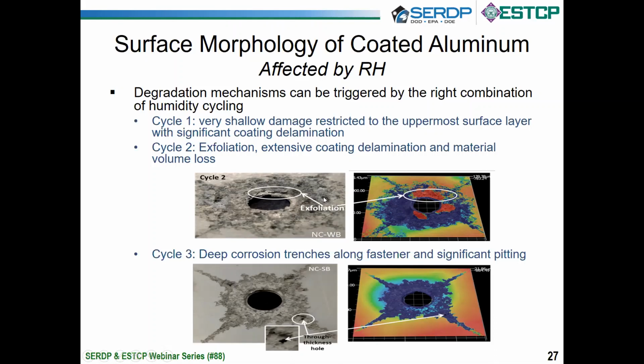And the thing that you notice in this test is that we see this exfoliation corrosion. These red things are above the plane of the surface. So we basically significantly exfoliated the surface. So all this stuff in blue is corrosion that happened, and the outline of this area is where we've delaminated coating. So there's no coating here and corrosion has occurred in this area.